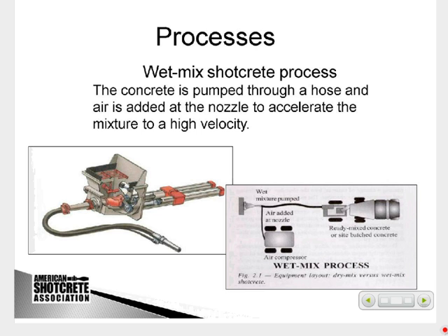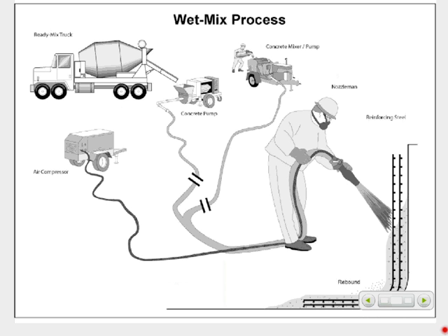Wet mix is the other process. This is the most prominent now. I see about 25% of the work is done in dry mix, 75% is wet mix. Wet mix takes a small concrete pump, and then pumps prehydrated, it's already mixed concrete, in through the hose. And then at the nozzle, we introduce air. The air pressure then is what conveys that concrete pump material at a high velocity out of the nozzle into the receiving surface. So the key here is the material is not dry, it's already wet.